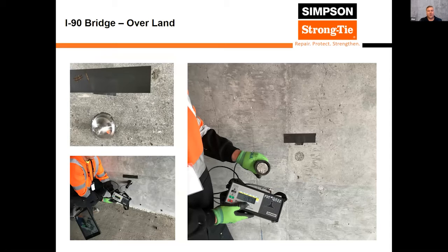So in these photos, we're looking at a pre-construction, or pre-installation, adhesion test, where they apply these test dollies directly to the concrete, let them cure up, and then eventually pull them off the substrate to show that they're getting a 200 PSI bond. And if you look very closely down here, you can see they got about 307 with very little substrate prep. So they are in very good shape for this project to apply FRP, and they know that that concrete is sound enough to actually apply FRP onto. This is actually going to be one of your field testing requirements after installation.